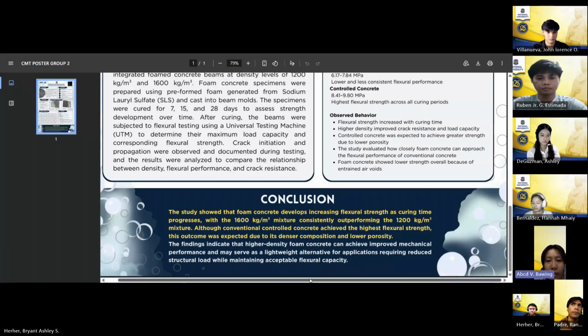We observed that higher density not only improves load capacity but also results in more complex branching crack patterns similar to conventional concrete, whereas the lower densities exhibit more brittle linear failure modes. Ultimately, this research confirms that SLS is an effective agent for producing stable, predictable foam concrete. We conclude that by optimizing density, specifically targeting 1,600 kilogram per cubic meter or higher, engineers can successfully balance the benefits of reduced weight with the mechanical requirements of modern structural applications.